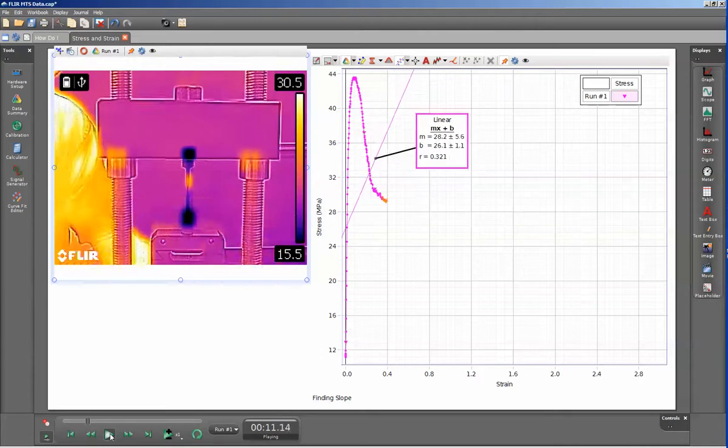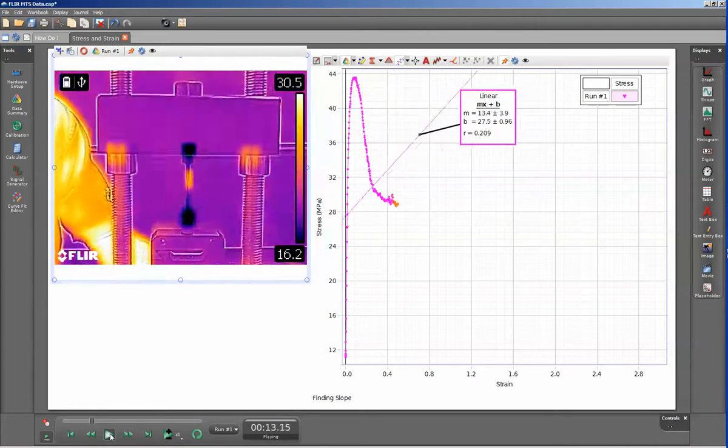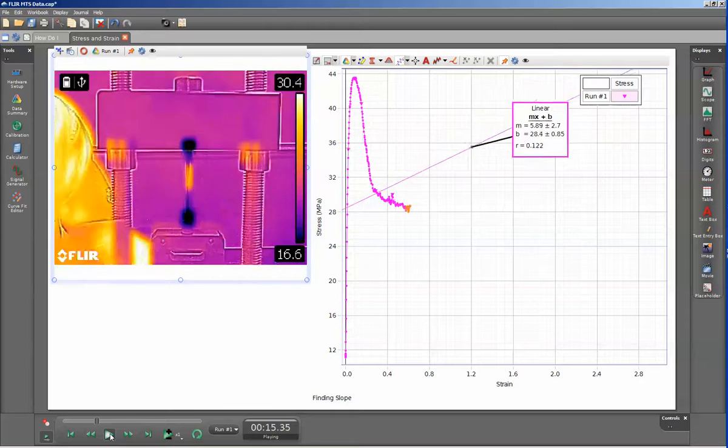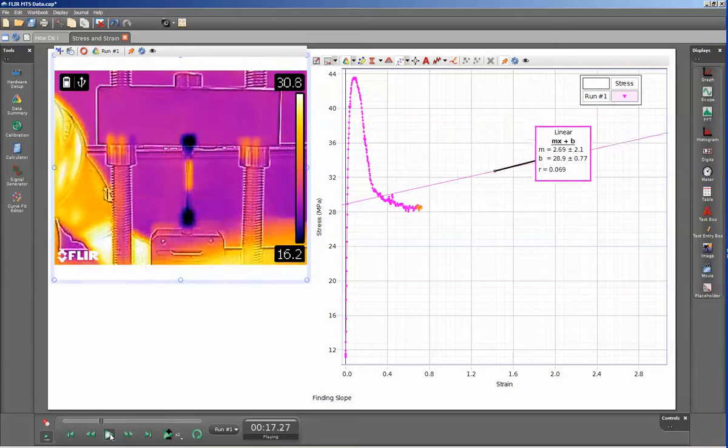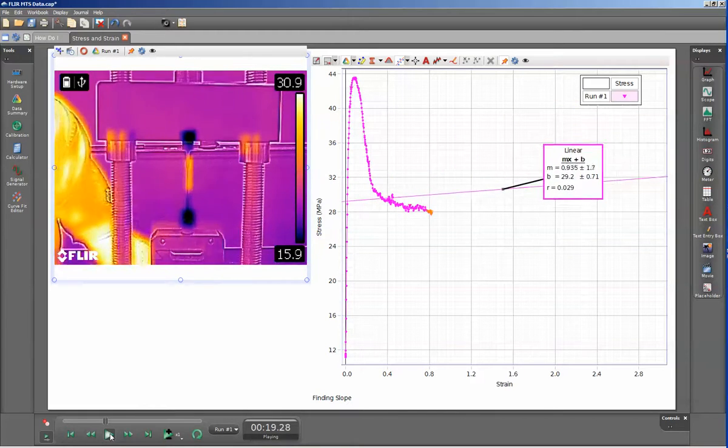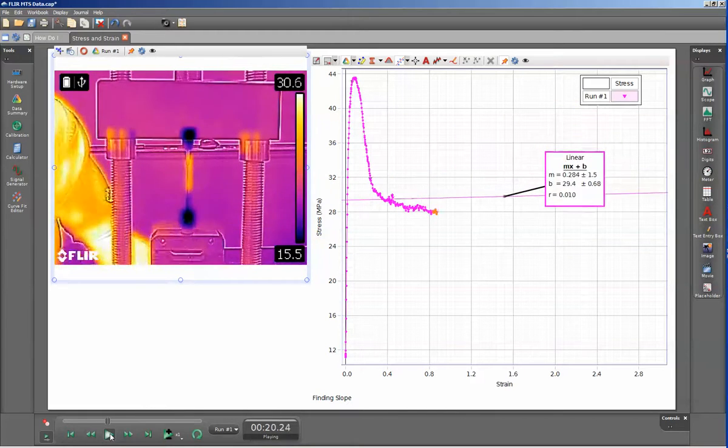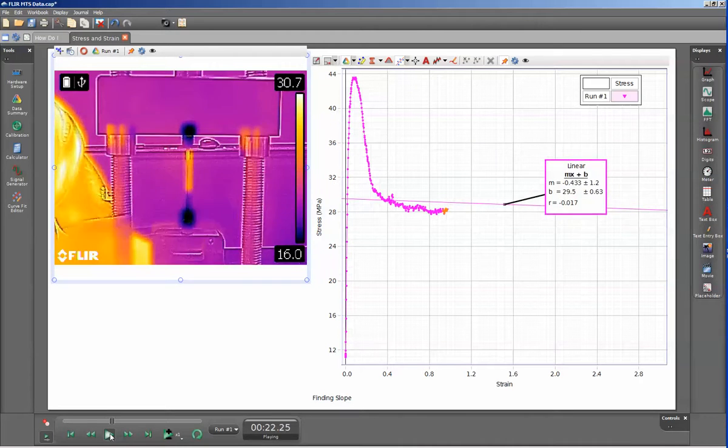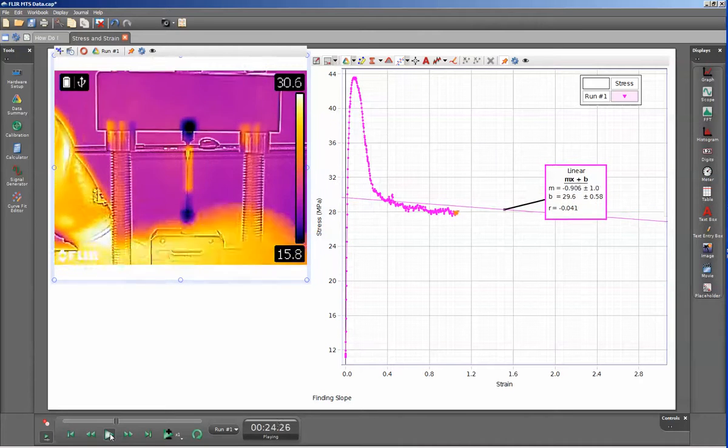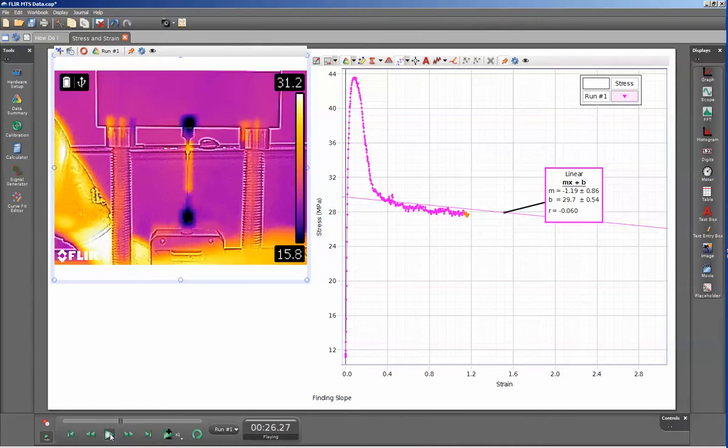Because of the nature of polyethylene, it's going to form a stable neck. We can see from the thermal camera that the primary deposition of energy happens in the deforming region that's going from the original cross-section of the sample into the much thinner necked region.